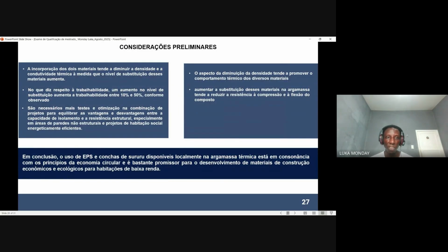The final consideration of this material clearly shows that as the substitution of this material tends to increase, the thermal conductivity of this material also tends to decrease. The density decreases, and the thermal conductivity decreases as the substitution increases, as seen in the literature. Next, the workability of these materials also tends to increase as the substitution level increases, which is clearly seen in the literature and also in the experimental results obtained.